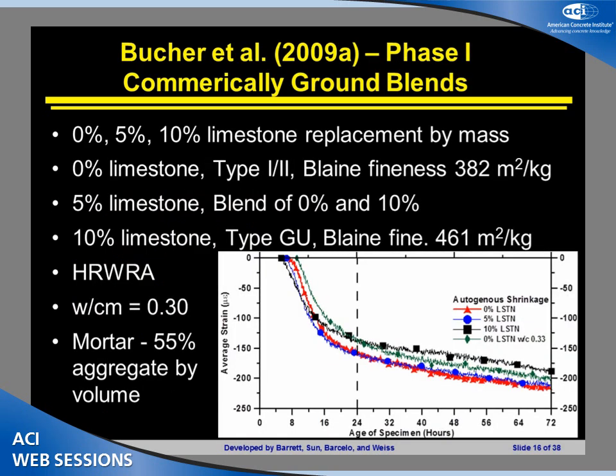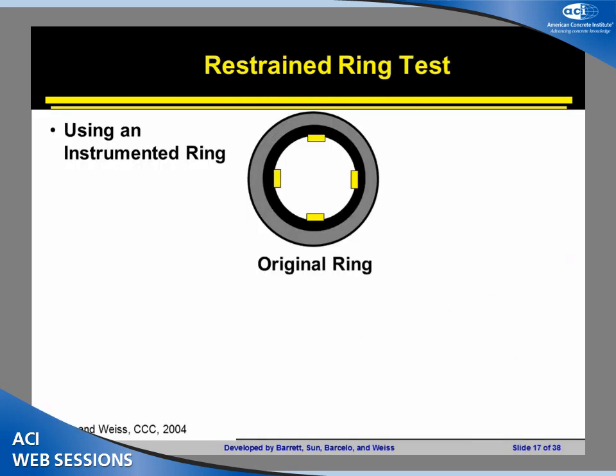So one of the first ones that we looked at, this is a commercially ground blended cement. Again, it's a Portland-Limestone cement, so it's been interground, looking at 0, 5, and 10% limestone additions. And essentially what we're going to look at here is the red line is 0% limestone, the blue line is 5%, the green line is essentially the effect of dilution, and the black line here is 10% limestone. And what we can notice if we look at the autogenous shrinkage here is we've got very similar shrinkage. All right, no additional shrinkage coming from the interground limestone, even though we see the Blaine fineness has gone from 382 up to 461. So even though it's finer, we're not seeing additional shrinkage in that system. Right. In addition to this, we've used a ring test, and I will come back to this a little bit later on.